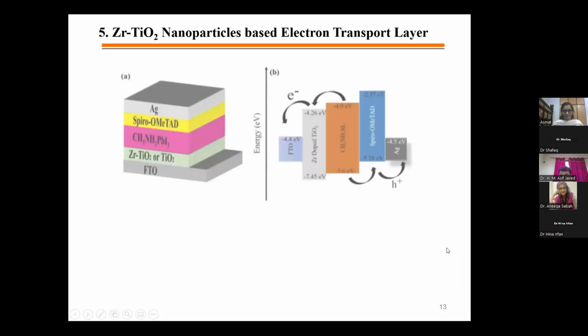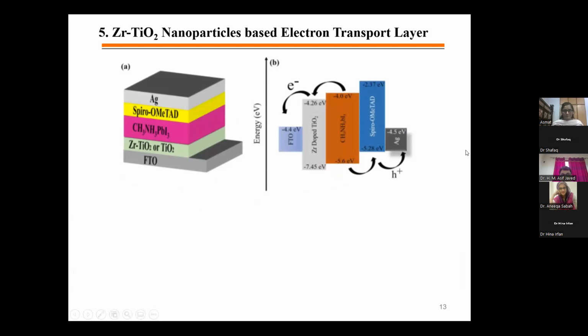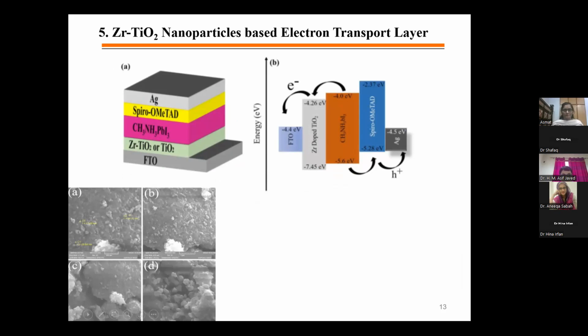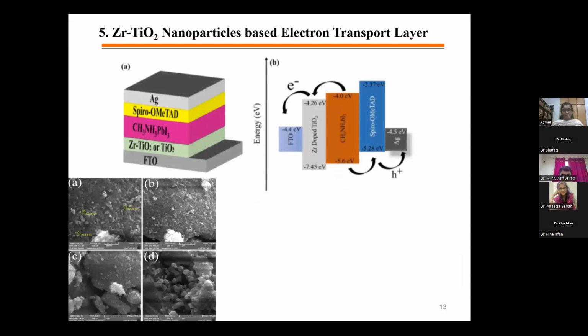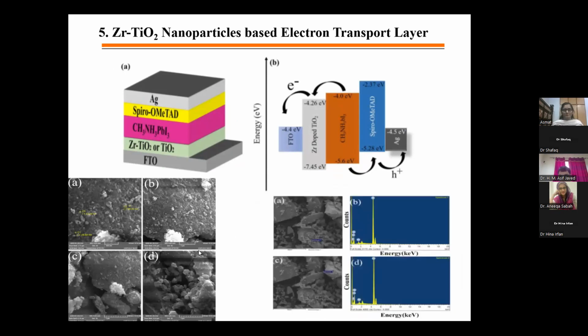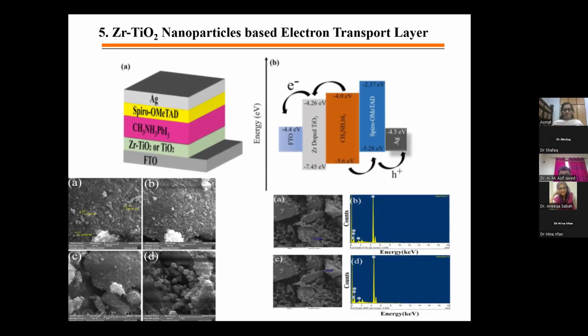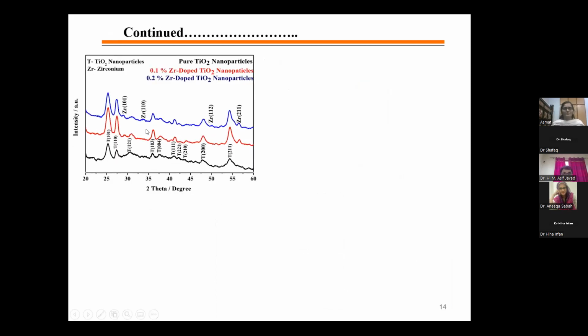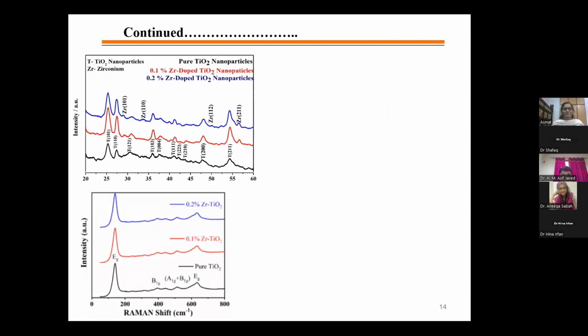This contribution is also extended to replace the material by zirconium, and the zirconium titanium nanoparticles-based solar cell has new advanced features, and we can see from here. These are the SEM pictures of the nanoparticles, and this is the EDX analysis of the zirconium titanium nano-based material, and the XRD analysis. The XRD pattern shows the zirconium nanoparticles, and the titanium nanoparticles have the same pattern as I mentioned before in the previous slides. The Raman spectra also confirmed the zirconium percentage of 0.1% and also 0.2%.